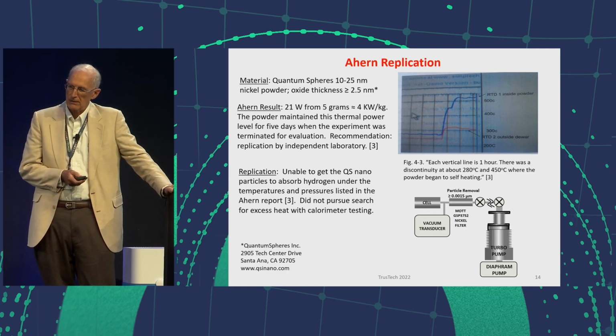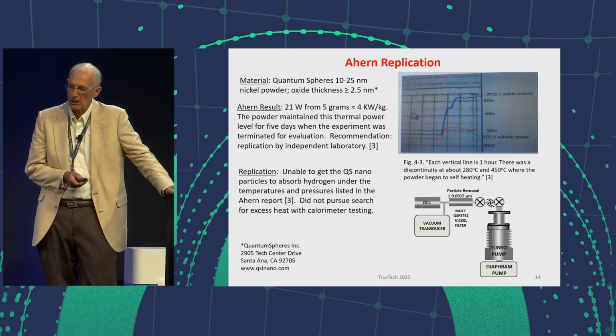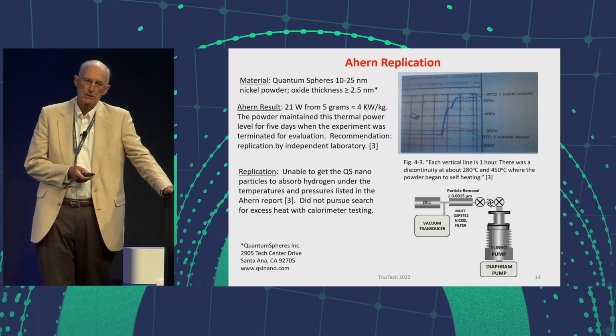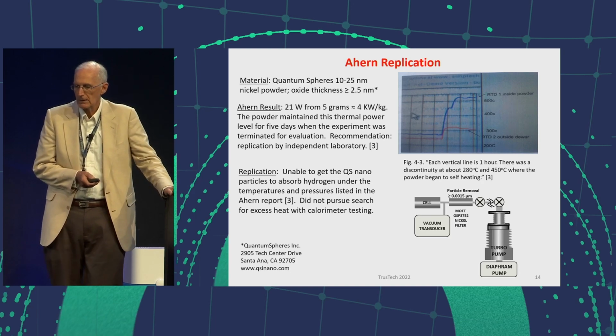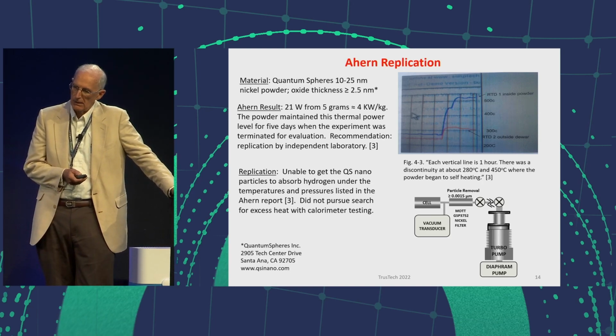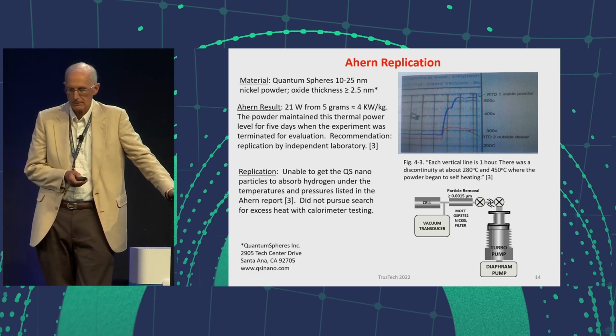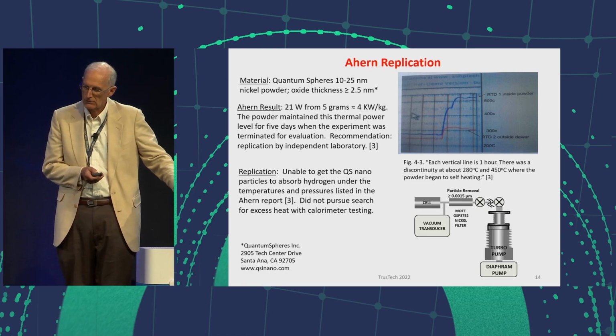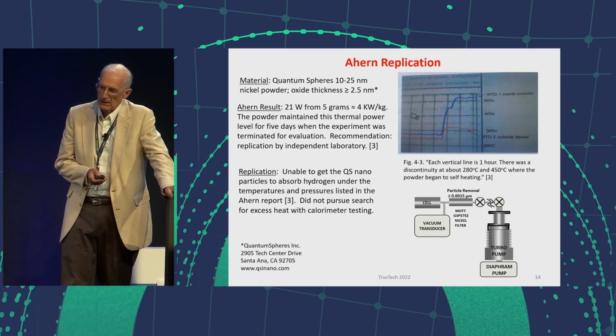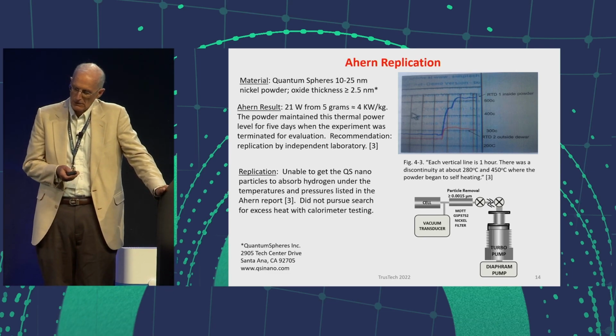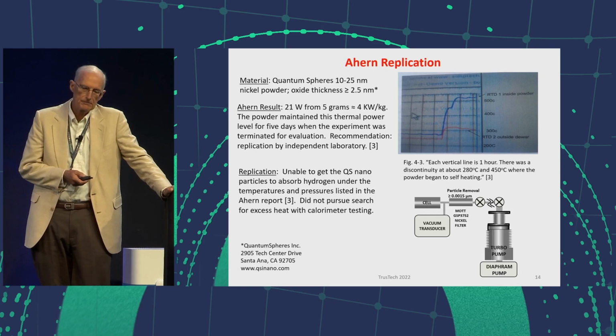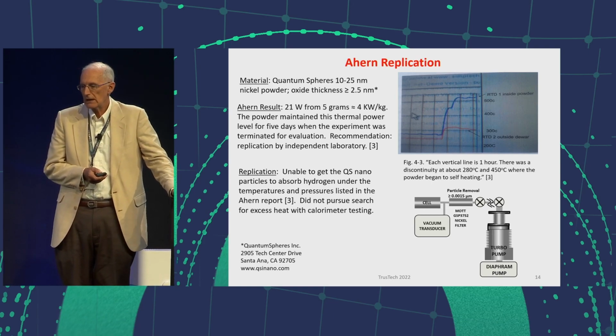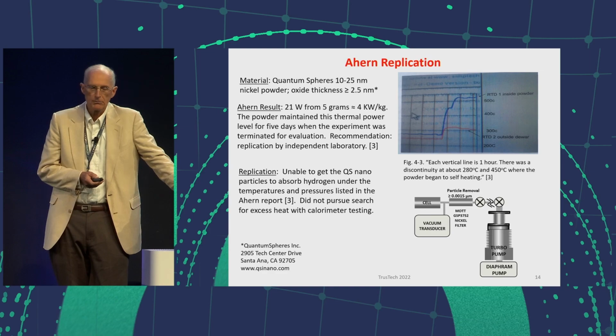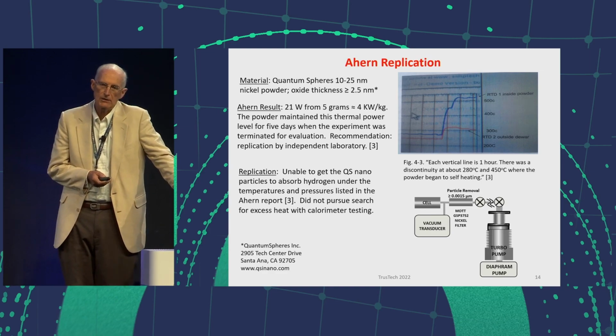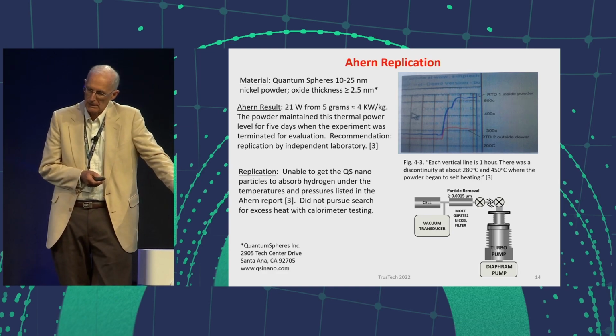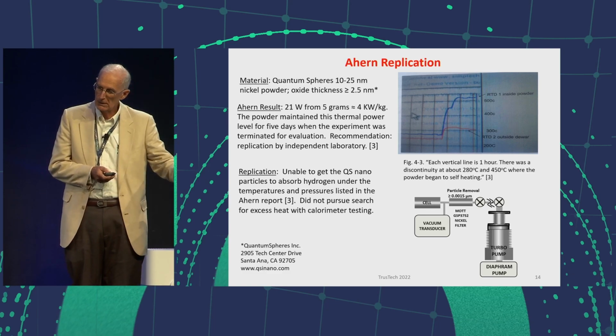These quantum spheres have diameters between 10 and 25 nanometers, and they have a thickness of 2.5 nanometers of oxide over them. The theory is that the 2.5 nanometers of oxide kept the material from sintering as it went to higher temperatures. My replication on this used a stainless steel cell, and I was never able to get any of the nickel material to absorb hydrogen. Without any absorption of hydrogen, it wasn't fruitful to go ahead and try to do calorimeter studies.